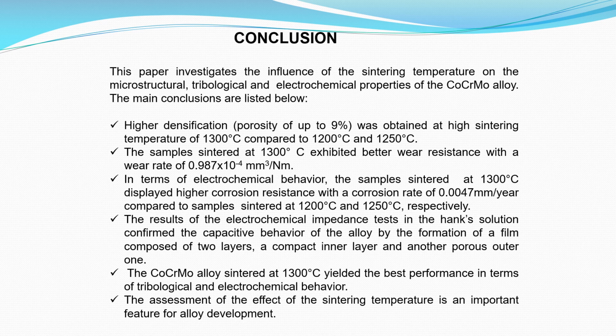On the other hand, the samples sintered at 1300 Celsius degrees yielded the best performance in terms of tribological and electrochemical behavior. And finally, we conclude that the assessment of the effect of the sintering temperature is a key element for the alloy development.